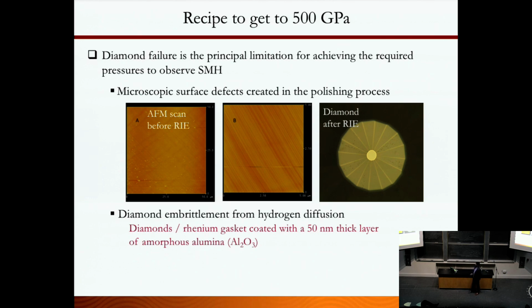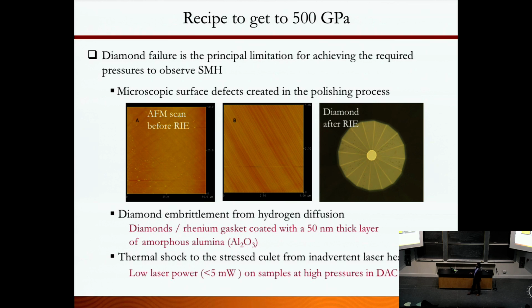So we found a way to prevent that: we put a small alumina coating on top of the diamond, so that it prevents hydrogen from diffusing into the diamond. Also, we use laser spectroscopic techniques, Raman and IR, Raman especially, to track the pressure. Laser shock can break the diamond, so we designed a new Raman system so that with small laser power we can still get a strong signal. Otherwise we're going to break the diamond. With this, and modifying our apparatus, getting perfect alignment, making sure the instabilities are not there, and refining the apparatus, we were able to generate really high pressures like 500 GPa.